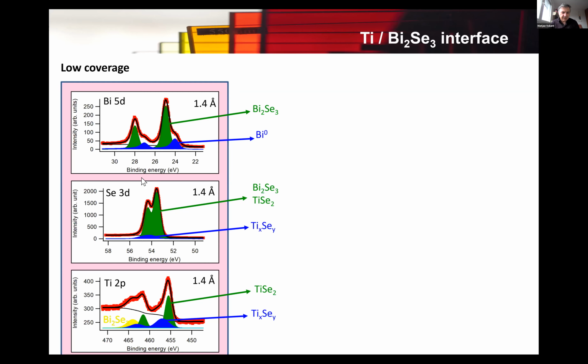We are also getting a different environment on selenium, which shows that some titanium selenide appears. And if you go to titanium, we can confirm this. Even easier, we see that instead of metallic titanium, we now can assign these peaks as corresponding to titanium selenides.